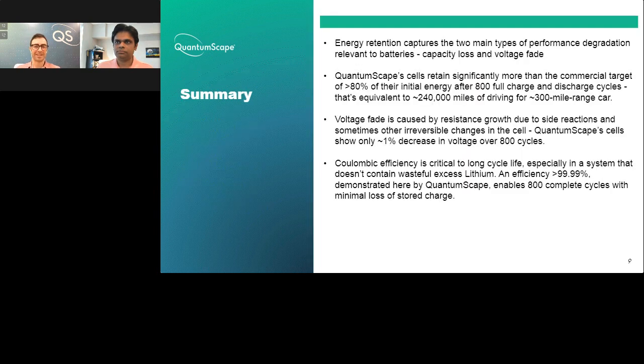Okay, so maybe now we can summarize for people. We talked about quite a bit, just to make sure that it landed with folks. We showed the energy retention of the cells across 800 cycles in a real strenuous test. And that energy retention captures the two main types of performance degradation that are relevant to batteries, both the capacity loss and voltage fade. And so we showed that these 3 cells that were tested under room temperature and otherwise reasonable conditions, and even accelerated conditions at 1 hour charge and discharge, retained 80% of their capacity over 800 cycles, which would correspond to north of 240,000 miles of driving if the car has a 300-mile range.